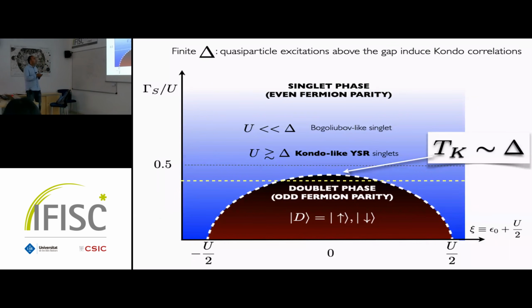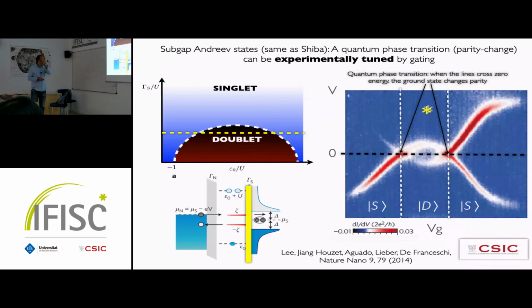All right, the point now is that if you fix the coupling to the superconductor, this gamma S, this is the yellow line, and you move the level position of the quantum dot, you can go from singlet to doublet to singlet. And this you can actually see in an experiment. This is experimental data from Silvano De Franceschi's group in Grenoble, taken by Eduardo Lee. This is a Nature Nano paper that we published a few years ago.